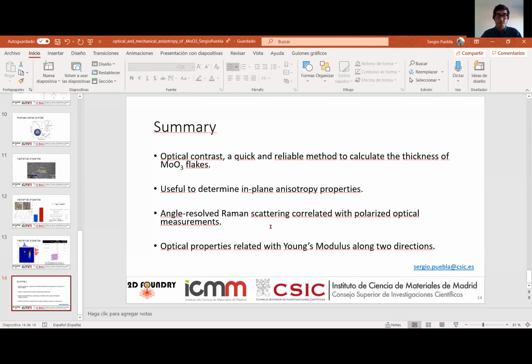Sergio, do you grow this material yourself? Yeah, we have grown it ourselves in our laboratory. We get molybdenum foils, and we set these foils in an oven in air atmosphere, and we heat up until 450 degrees Celsius. The molybdenum trioxide flakes start to grow onto a silicon wafer that we have placed onto the molybdenum foil, and then we transfer these flakes with PDMS with a deterministic transfer setup onto the silicon dioxide substrate that we have already shown.